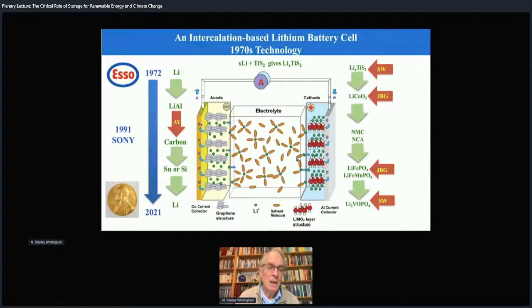Okay, a little bit of history here. Back at Exxon in the 1970s, we used pure lithium metal. It tends to form dendrites. These are spiky protuberances that go across the cell and short it out. So Exxon pretty quickly switched to lithium aluminum, which works well for maybe 50 charges. But it was Akira Yoshino who discovered that various carbons with a graphitic phase could store the lithium, and that's what I actually show you here.